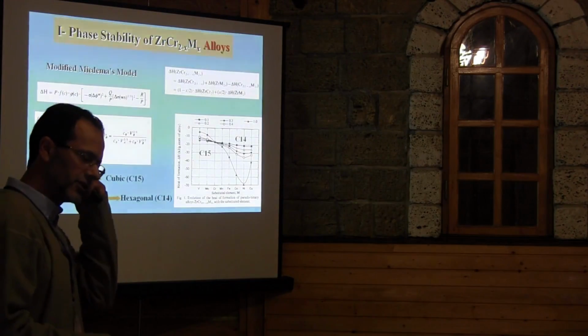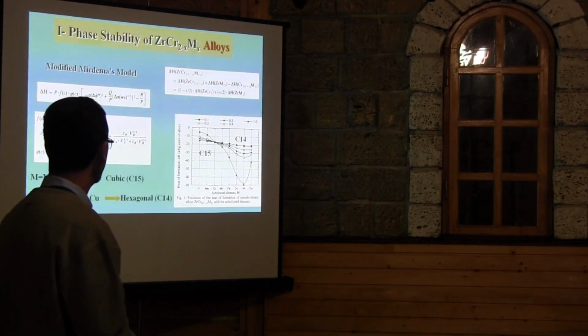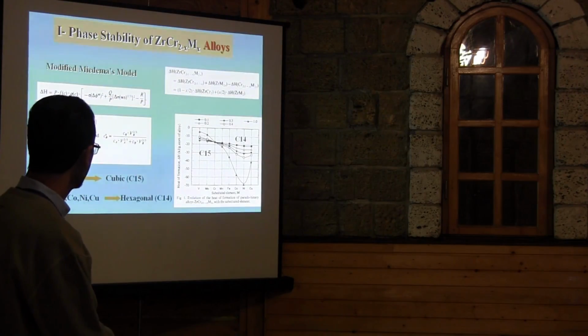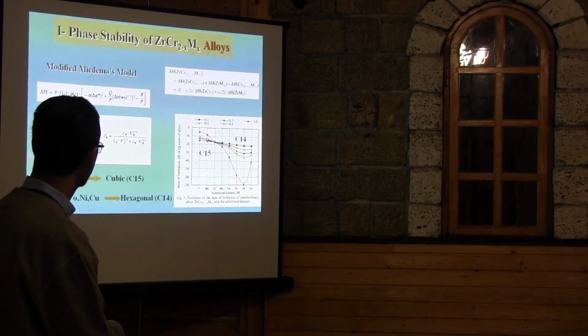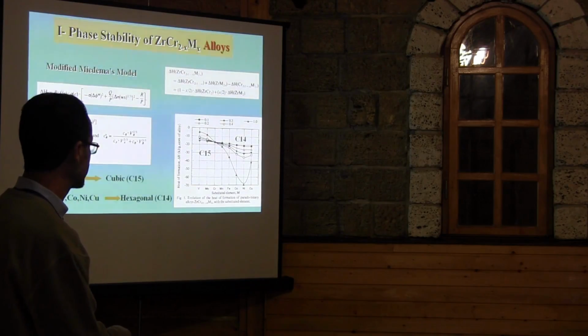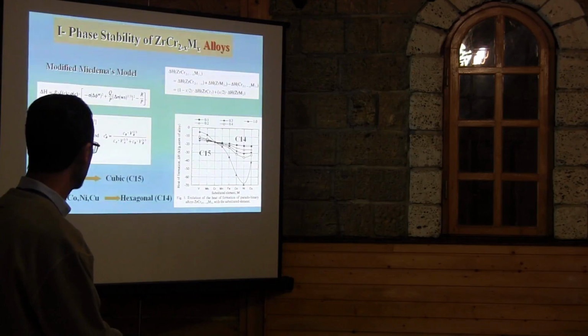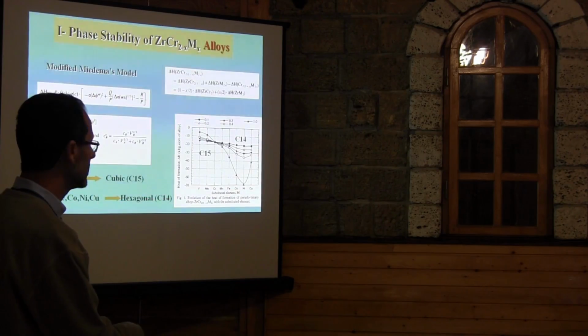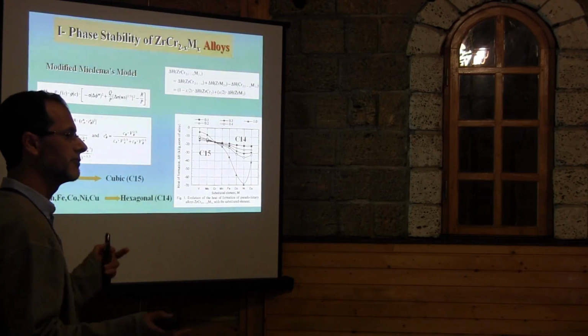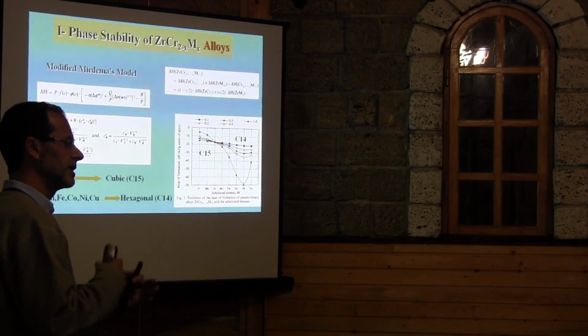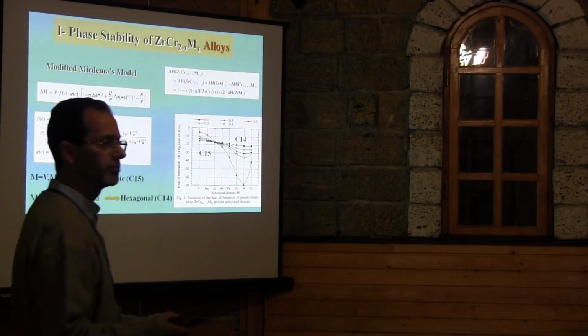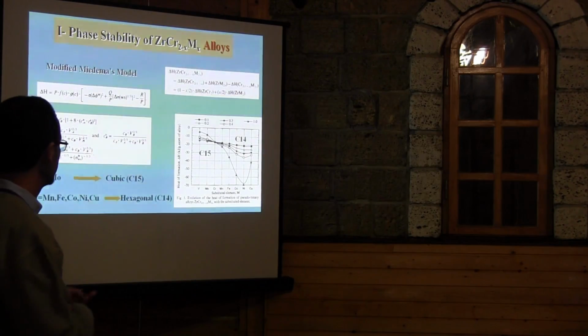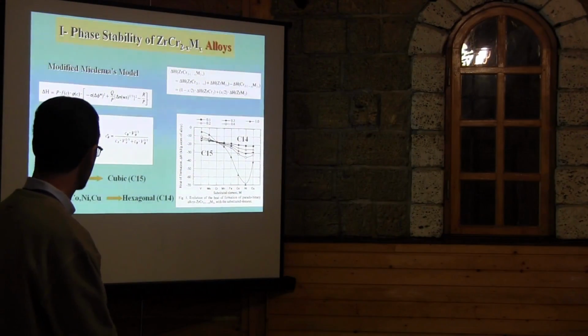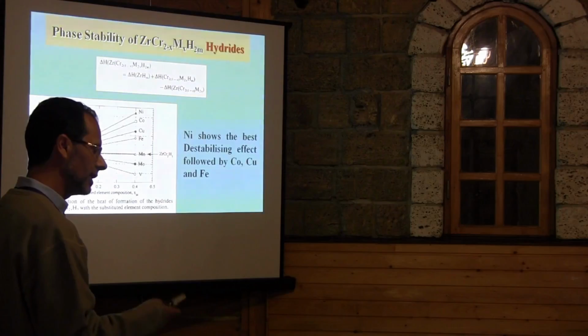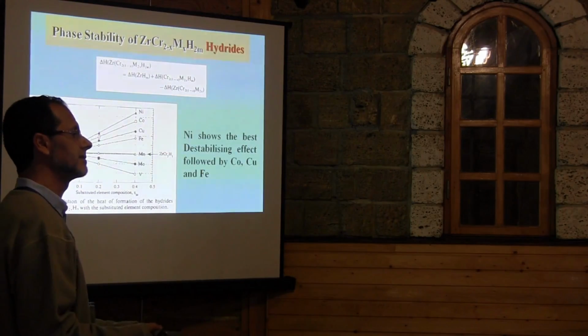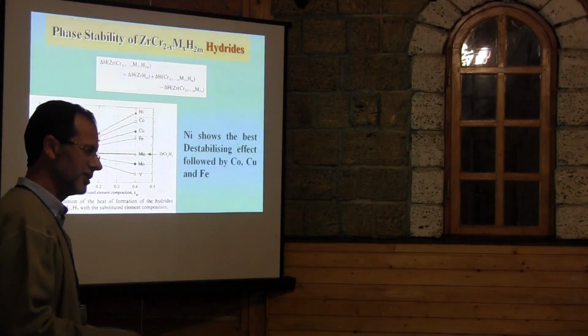So I did some theoretical investigation, and I can see that depending on the element, if I replace zirconium by molybdenum or vanadium, I stabilize the cubic phase. Okay, you can see here. But if I put another transition metal, from manganese, etc., I stabilize the hexagonal. So this is interesting for me, that I can play with the substitution or with the chemical composition to change from cubic to hexagonal. This will affect, of course, the hydrogen storage capacity. Again, when I put these elements, how does this affect my interaction with hydrogen? Is it good or bad?